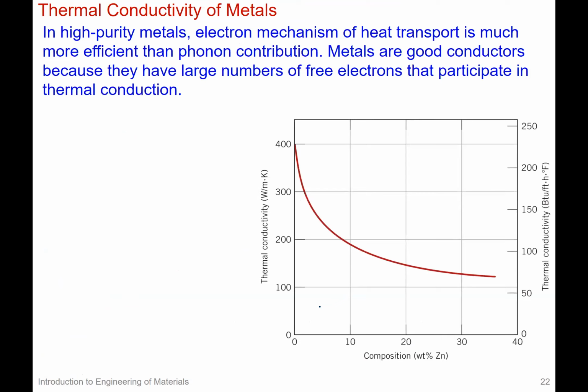For thermal conductivity in metals, especially high purity metals, the electron mechanism of heat transport really dominates and is much more efficient than the phonon contribution. Thus, metals are good conductors because they have a large number of free electrons that participate in thermal conduction. And if you have high purity metals, you really don't have imperfections to scatter these electrons, so they're really good heat conductors. If you have ultra high pure copper, it's a really good conductor for that reason.